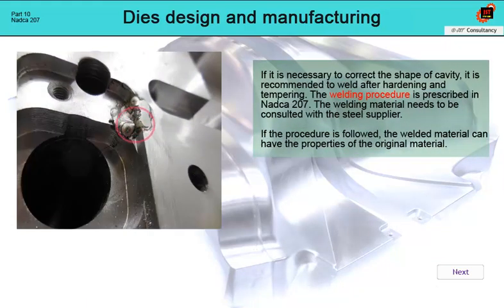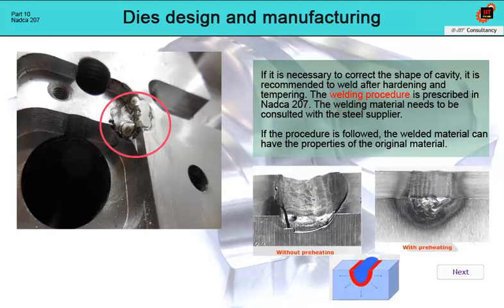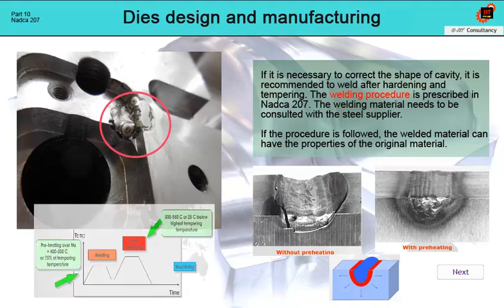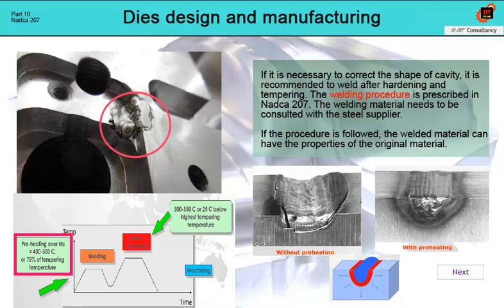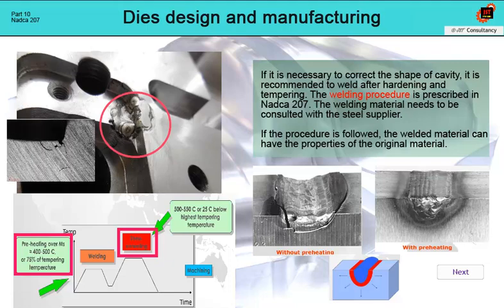It is used to correct a faulty machining process, or to change the cavity after testing to achieve the correct dimensions of the insert. Therefore, this process cannot, with exceptions, be predicted in advance. For welding before quenching, a different procedure and electrode is needed than for welding after quenching. If we really have to weld, then the insert needs to be preheated to a temperature above martensite start, optimally 400 to 500 Celsius, and then annealed to remove stress. If this procedure is followed, it is possible to obtain a weld with material properties close to those of the compact die material. If not, then it is the source of catastrophic cracks.